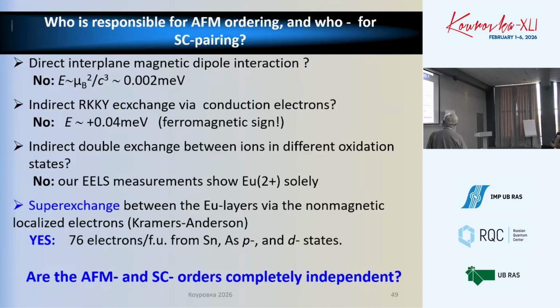Then indirect RKKY exchange via the conduction electrons, the issue that bothered us, is also quite tricky because it decays exponentially with distance, and moreover, it oscillates. At the given distance between europium layers, it is on the ferromagnetic side. So the conduction electrons are not actually effective in setting the magnetic order. And this may most clearly explain how the superconducting pairing and magnetic ordering coexist. Now, the most important is superexchange between europium layers via the non-magnetic localized electrons with the p and d states of deeper shells of tin and arsenic.